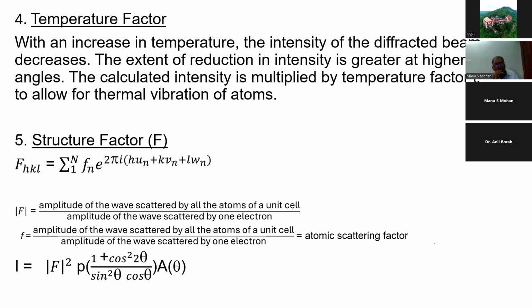So now if you take all these factors, you basically get F square P, where intensity is a product of the structure factor. Your F square means only the amplitude you are considering here. So it's the modulus of the structure factor squared, times the multiplicity, times the Lorentz polarization factor, times the absorption factor.